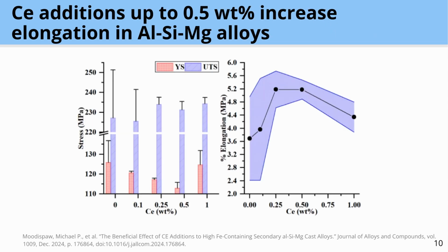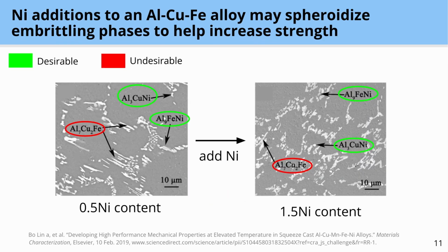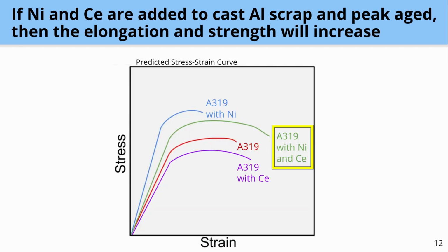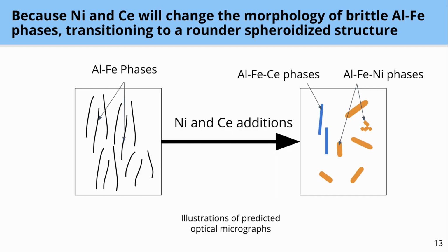By doing research, we found that cerium additions up to 0.5 weight% can increase elongation in aluminum, silicon, magnesium alloys, and nickel additions in aluminum, copper, iron alloys help spheroidize the embrittling phases and will increase the strength. So our hypothesis is that if we can add nickel and cerium additions into our 319 scrap alloy and peak age it, then the elongation and the strength will increase to make it a desirable structural alloy. And this is because the nickel and the cerium will change the morphology of the brittle aluminum iron phases and turn them into rounder spheroidized structures.